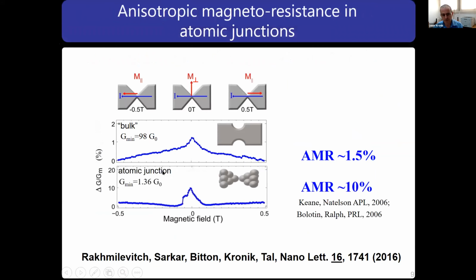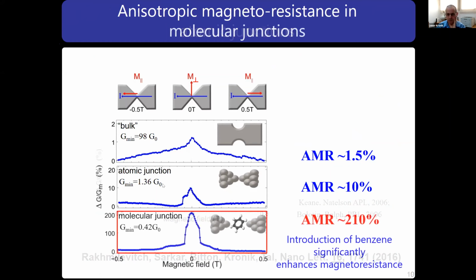Two different groups have shown already 15 years ago or so that if you take this down to an atomic junction, it's a larger effect. It's about 10%. But with this benzene molecule in the middle, Oren's group was actually able to measure an effect of more than 200%. So that is a huge effect, which obviously got our attention. And we wanted to see if we can contribute to its theoretical explanation.